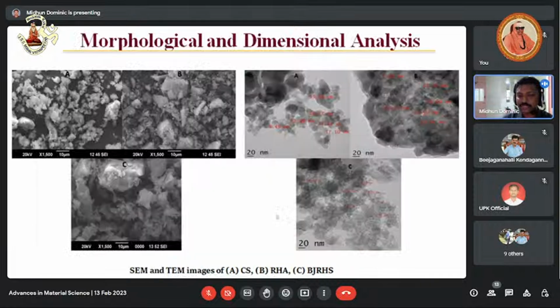And SEM analysis was conducted to know the shape and the surface morphology. All the samples are highly agglomerated because the silica has a number of silanol groups, OH groups, on its surface. Because of the formation of hydrogen bonding between the silica particles, these particles are highly agglomerated. TEM images also show agglomerated silica particles. So SEM and TEM are actually used to determine the particle size.